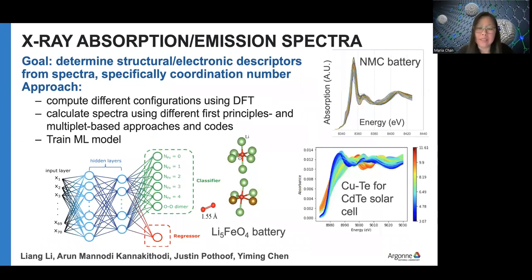In the cases that we have studied, they involve things like an oxygen atom in a lithium battery material that undergoes a lot of reorganization, even oxygen evolution. So we're trying to pick out whether the oxygen is turning peroxide, whether oxygen has a lot of transition metal neighbors or purely lithium neighbors, which is conducive to oxygen redox.